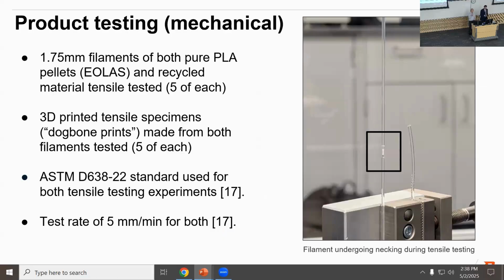Once we were finally able to produce some filament within the diameter that we wanted, we created 5 samples of both the purchased material and our recycled material for tensile testing. We also 3D printed some specimens known as dog bones that are used for tensile testing. We did 5 of each of those in both materials. And we used the ASTM D638-22 engineering standard for testing the polymers at a rate of 5 millimeters per minute.